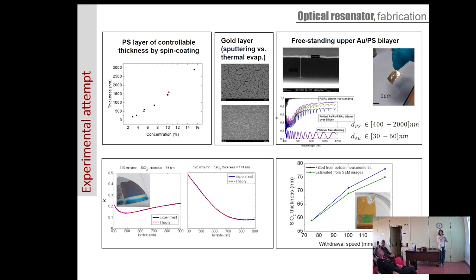Okay, so I will go very fast because it didn't work out. Tell me, what happens with the van der Waals force? It's the same. It's the limit at very short distances, when you don't take into account retardation effects. So, are we measuring a Casimir-Lifshitz or a van der Waals force? Casimir-Lifshitz, because we are at a larger distance, where you have to include a retardation effect.